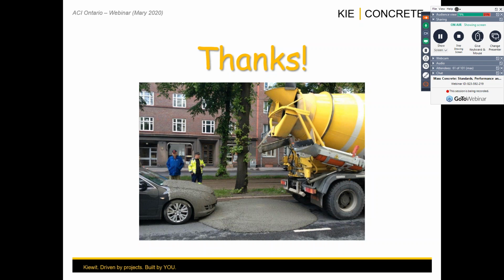Well, you know, it's all about chemistry, and the chemistries and amount of cementitious materials, supplementary cementitious materials in precast are completely different to cast in place mass concrete. So it's all about what are the materials you're using. I cannot tell you that the temperatures need to be the same. Yeah, they need to be the same if they have the same materials. I don't see why we need to differentiate in this case between the accelerated heat of hydration to the same of a mass concrete heat of hydration.